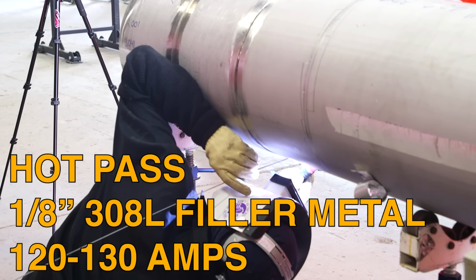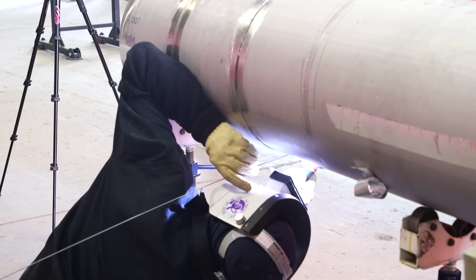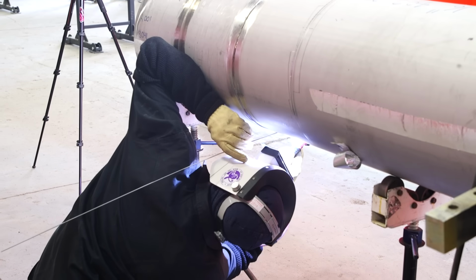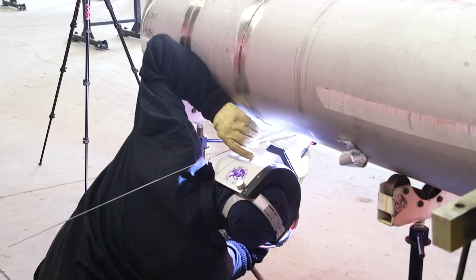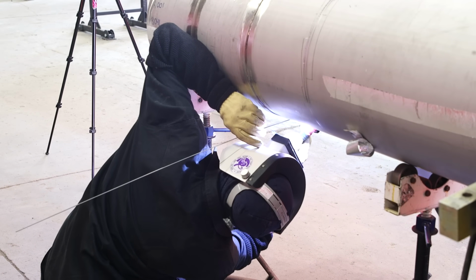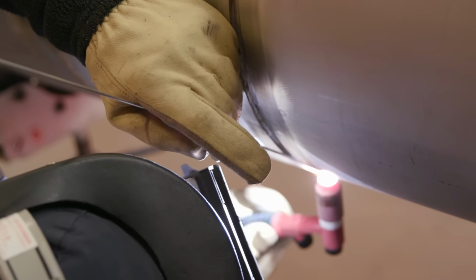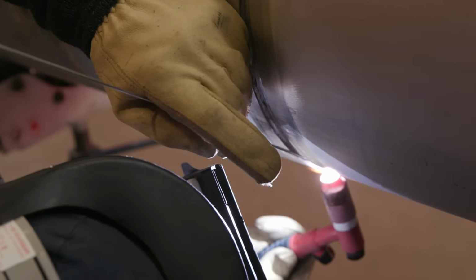Basically what we're doing here, this is just a hot pass. It's a little bit hotter than the root pass, just to get nice fusion and wash the weld puddle out. So essentially I'm making the fill relatively uniform, so if I have any misalignment or anything like that, the deposit metal is equal on both bevels. So if one comes down more than the other, the weld puddle I'll have to come down so there's equal fill on the bevels.